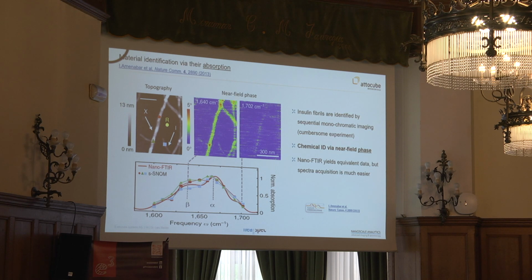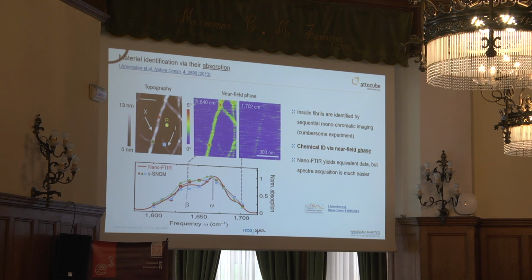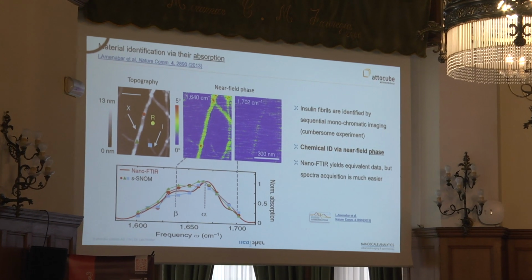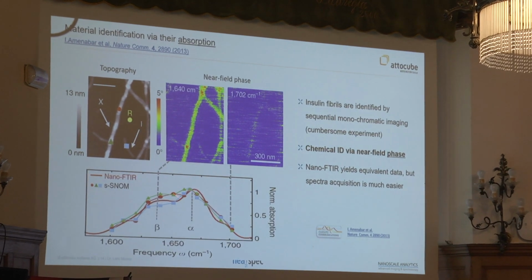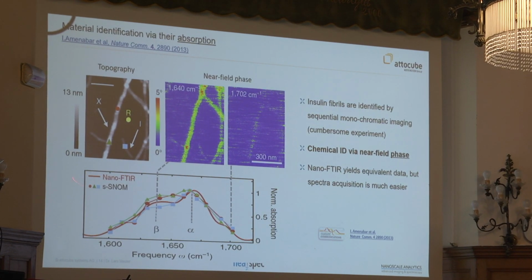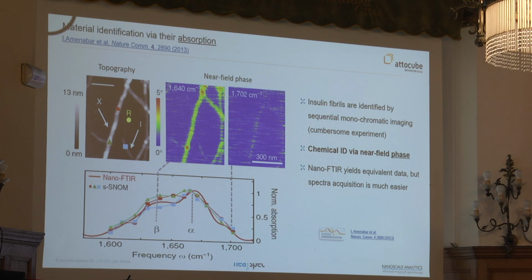but the spectra nicely overlap. So they contain, in principle, the same information, and if you keep all experimental settings and parameters the same, you also get the same number. So let's say this is 50 degrees high. It doesn't depend on what laser you use. You should get a contrast of 50 degrees, which then also can be described by a model.